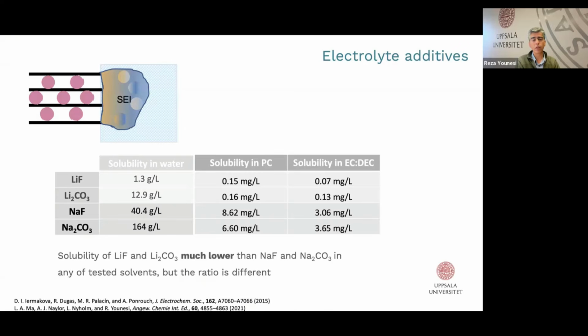But when it comes to organic solvents like PC and EC:DEC, it's more difficult to measure solubility, but still you can see that the numbers differ depending on what species we are measuring. For example, sodium fluoride has slightly higher solubility compared to sodium carbonate. Another interesting point is that lithium species, at least these two lithium compounds, have much lower solubility compared to sodium compounds, which is in line with the fact that we expect the SEI species of sodium-ion batteries are more soluble than those of lithium-ion batteries. This is a bigger problem for sodium-ion batteries compared to lithium-ion batteries, but it's possible to address this issue if we understand the system properly.